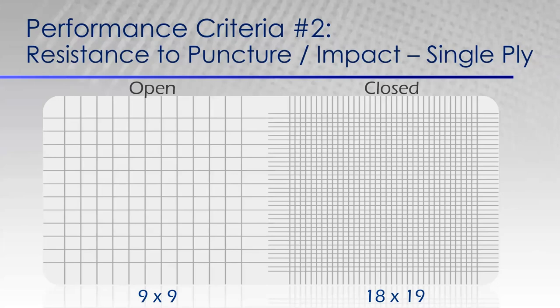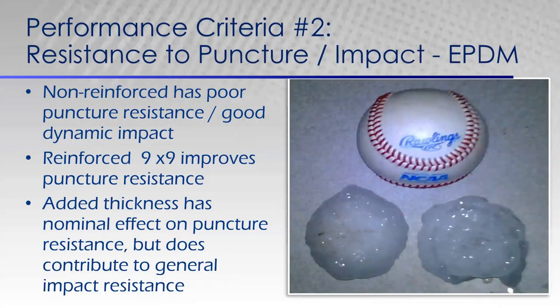So it's a safety kind of parallel there per se. So let's look at EPDM. Some of the EPDM was non-reinforced, so puncture resistance was just terrible on it. But its thickness does provide good dynamic impact. So what they did was they reinforced EPDM with that 9x9 open weave to help provide that puncture resistance and that elongation in the movement on the roof to keep it in place and keep it performing well for your roof.